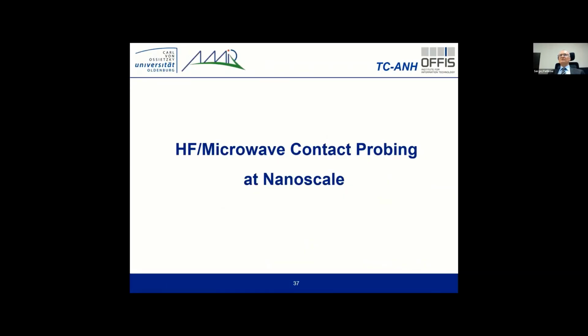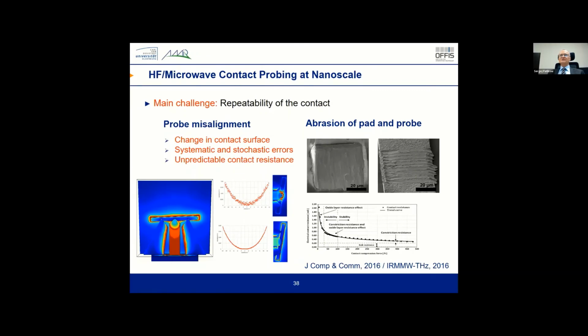High frequency microwave contact probing. So this is another interesting piece of work. This is about scanning microwave microscopy, high frequency measurement, and the influence of misalignment. You can see here the simulation of misalignment of the ground-source-ground probe. If you have a little bit of rotation, parasitic rotation, you immediately have deviation from the expected signal.